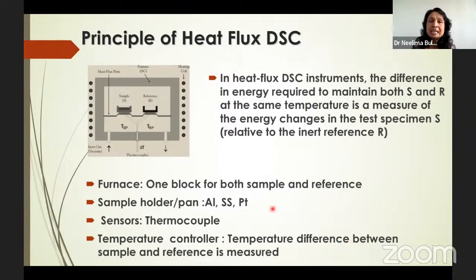In heat flux, for the major difference, I'll tell you, there is one block where your sample and reference are sitting, with a single heater. The sensor here is a thermocouple. And what you do is measure the temperature difference between the sample and reference. That much simple. Whenever a transition occurs in the sample, there will be a temperature difference, which is measured by the heat flux. So in very simple language, it measures the difference between the sample and reference.